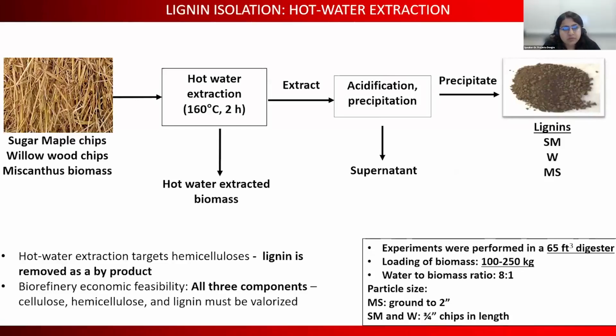So moving to the lignin that we use for making our resins, we isolated lignin from hot water extraction. Now, it is important to note that the hot water extraction process primarily targets hemicelluloses, and lignin is removed as a byproduct. Since it is important for the biorefinery to become economically feasible that all three components should be valorized, we decided to take the lignin byproduct from this process to make the resins.